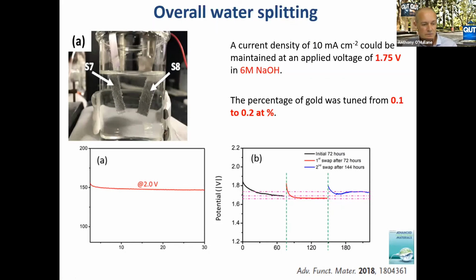This bodes well for direct integration with renewable electricity. The other advantage is that we're only using 0.1 to 0.2 atomic percent of gold, so in terms of cost this certainly won't blow out the cost of your catalyst, especially as we're using stainless steel, which is relatively cheap. We're quite confident about this one, and we're looking to scale this into a 2 kilowatt electrolyzer, and have that out at our pilot plant to see how it goes over weeks and months - that's the coming research in that particular area.